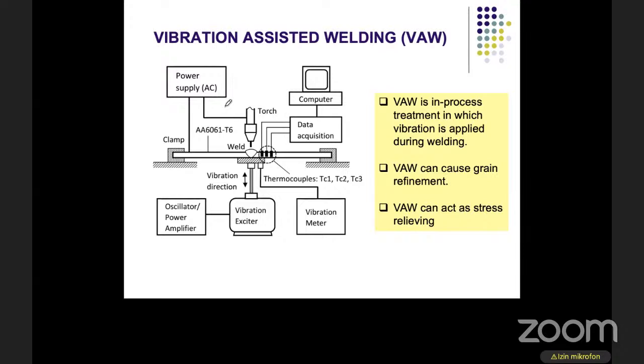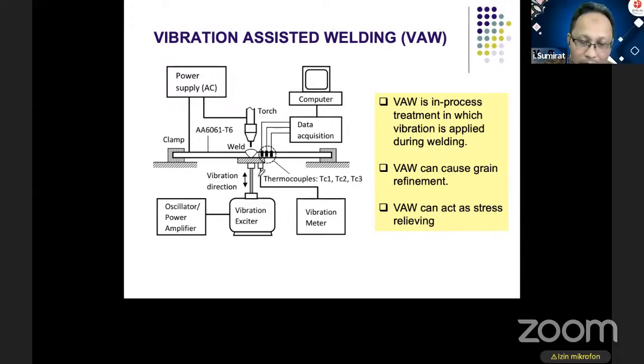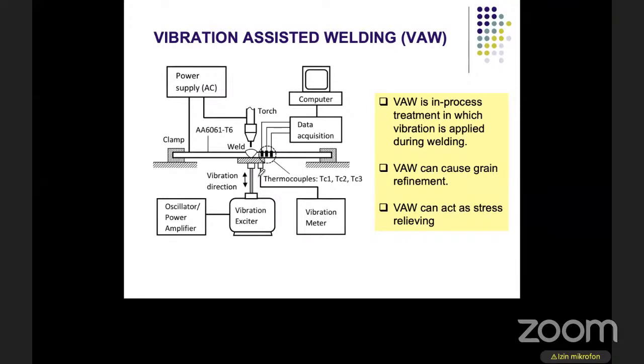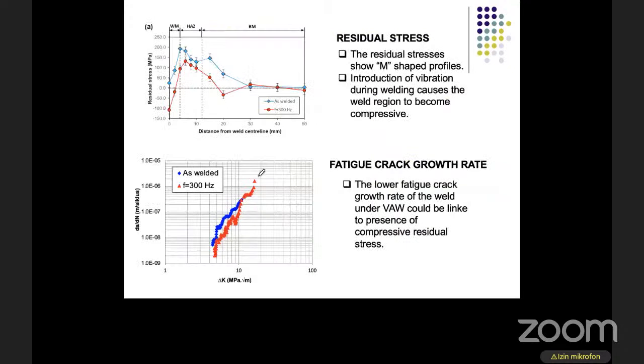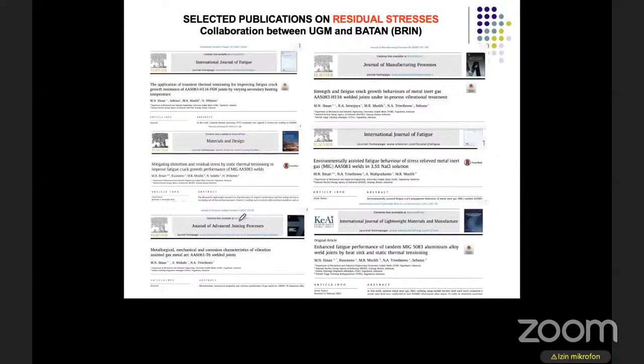Here we use local vibration assisted welding, where vibration is applied to the welding process, and we can see that the use of vibration during welding reduces the residual stress here, accompanied by better fatigue crack growth performance. And that is the end of my presentation. These are some papers that have resulted from the collaboration between my university and BRIN. I think that's all. Thanks.